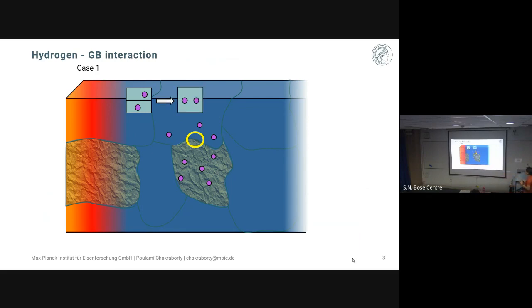Generally, we see that they have a tendency to segregate at the grain boundary, because at the grain boundary, due to different types of orientations and stress, there is a misfit strain accumulated, because of which the interface becomes much more important, and interesting mechanisms happen there. One of them is segregation to the grain boundary, and they like to sit there.